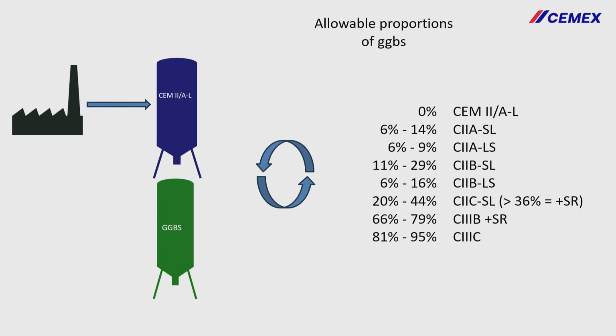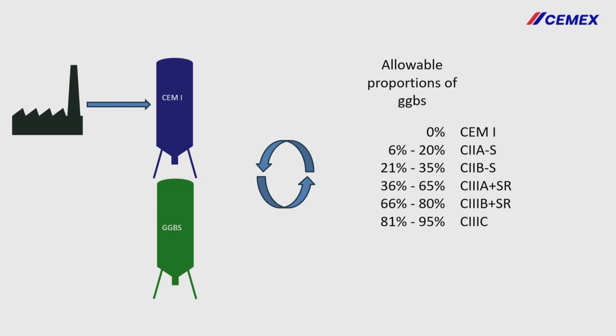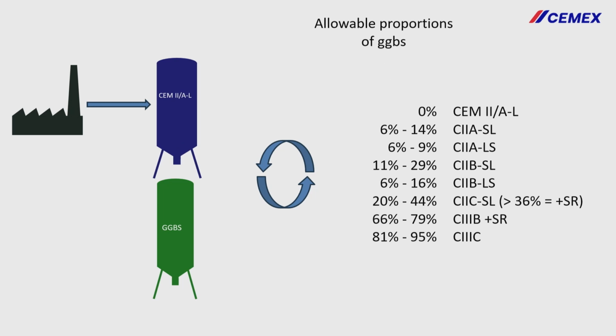Pre-November 2023, we could only blend GGBS at less than 36%. So those that are familiar with design chemical classes, that means you couldn't produce a plus SR concrete, okay? So you could only produce it for a few exposure classes. Moving forward, what we are doing as Cemex, and what others are doing in the industry, is stocking CEM II/A-L at our concrete plants, a lower clinker cement already, and then combining it with GGBS, thus giving these new cement designations, okay? The most common one will be CIIC-SL, and plus SR when it's greater than 36%. So previously we had CEM I, CIIA-S all the way to CIIIC. We've now got these, okay, CIIA-SL, again, all the way through to CIIIC.